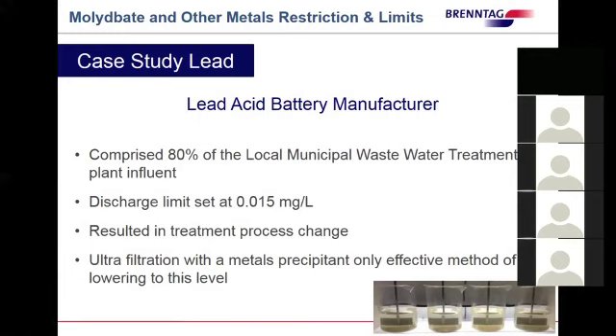So the conventional chemistry was no longer effective and resulted in a change in their process. They went to ultrafiltration and initially tried to treat the waste stream with just ultrafiltration alone, and they were not successful in getting down to these new limits. So we then looked at a metals precipitant in front of the ultrafiltration unit. We were able to successfully get them down to where they needed to be, but as a result of precipitating more lead, we saw that the ultrafilter was blinding faster than it had.